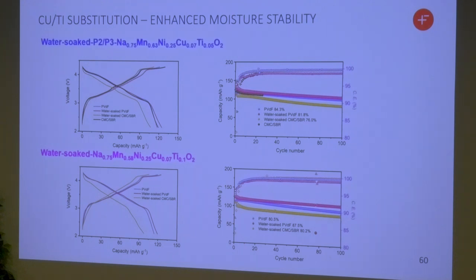Now, one of the drivers for looking at copper and titanium, both are said to make the material more stable with respect to moisture. So my postdoc put some of our material in water, left it for 10 days, took it out, dried it, and it cycles incredibly well. In fact, this material cycles better after it's been soaked in water, which is not something I'd necessarily recommend, but it does give us the possibility that instead of using nasty organic solvents to prepare our electrode materials, we can actually do it in a water-based system, which would be much more environmentally friendly, much cheaper.